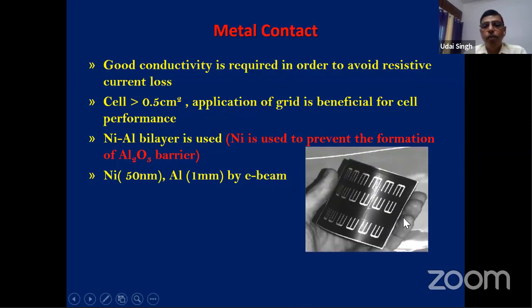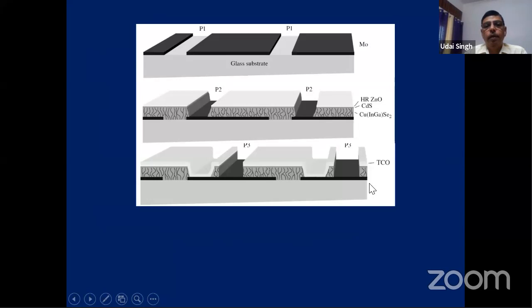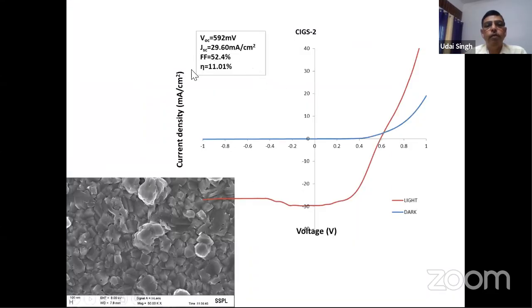Okay, so at lab scale, we try to make small cells for the measurement. And if you are having a module, you can integrate that module by laser scribing. You start with the glass substrate, then you scribe it, you isolate the moly, then you deposit the copper, indium, gallium selenide, and high resistive zinc oxide. After that, again you have the second scribing isolation, and then finally you coat the TCO, then you have the different cells. So here an interconnect is possible only on the large area, but in silicon, you have to have different solar cells, and then you have to integrate. This is one of the devices we have developed under the DRDO project, with around 11.1% efficiency.